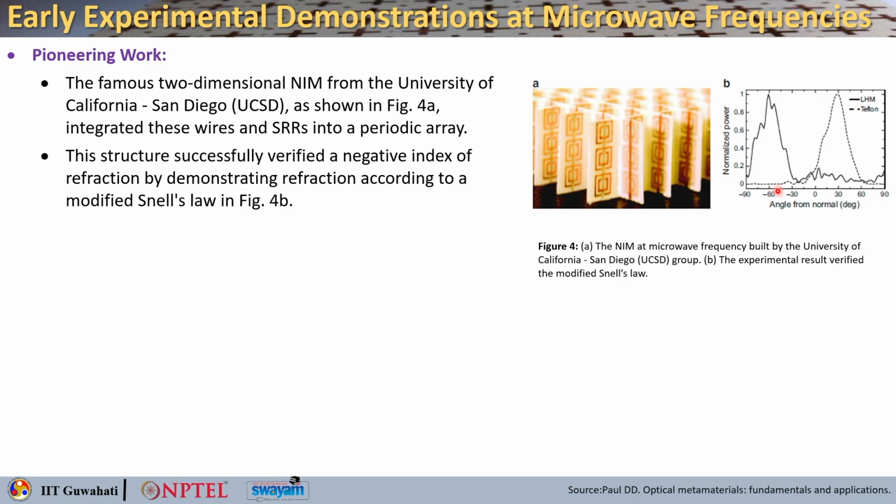But on the other hand, if you look into the left hand material sample, the peak was recorded at minus 61, okay, from which you can deduce the index of refraction to be minus 2.7 plus minus 0.1. So, this is telling you that negative index material is going to give you negative refraction.